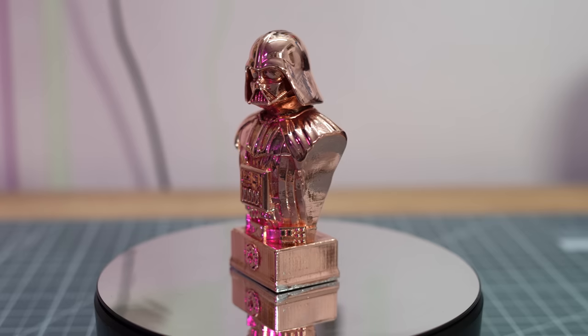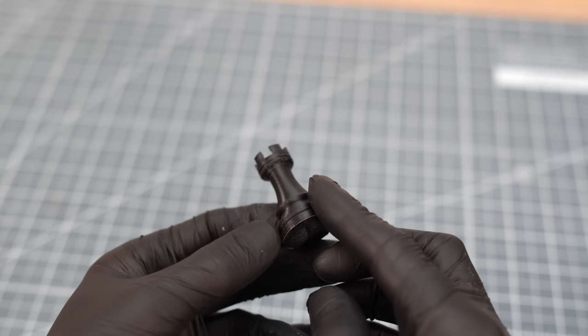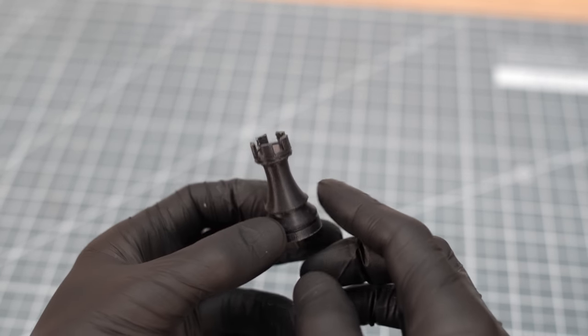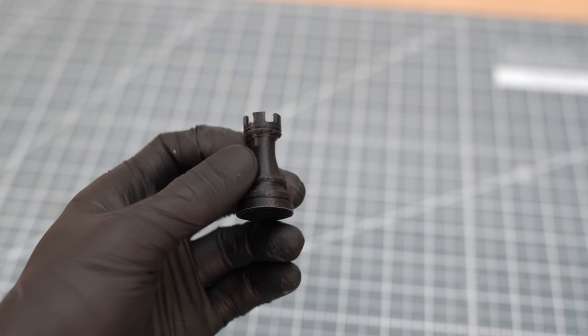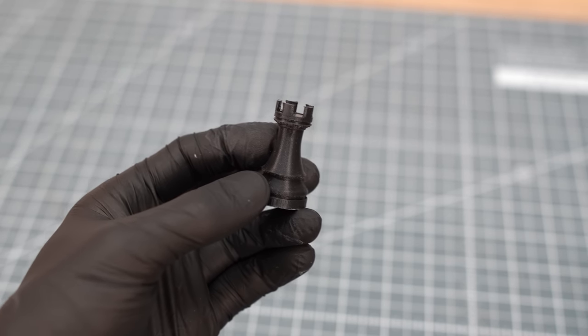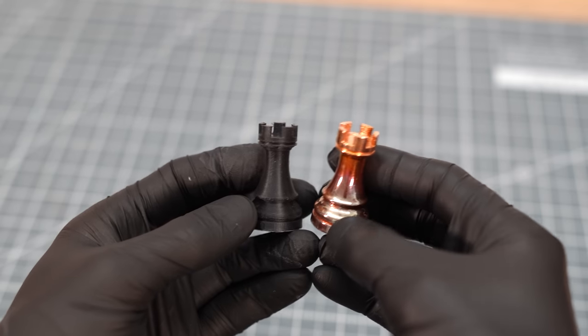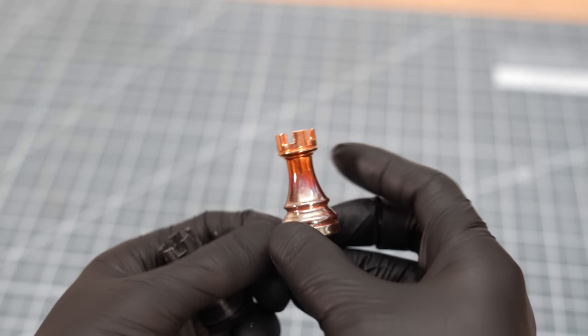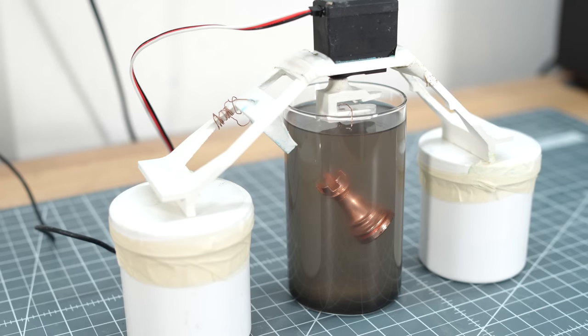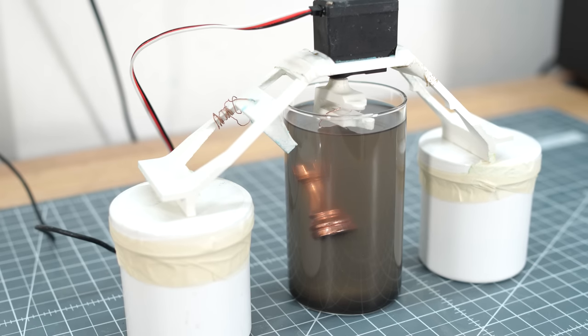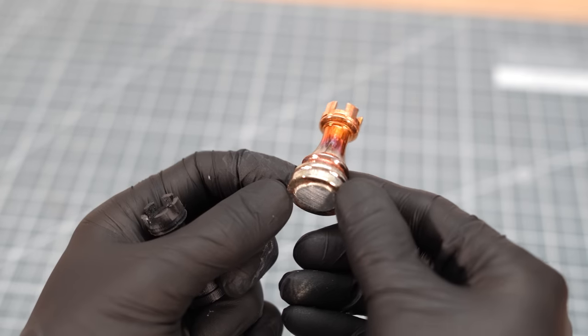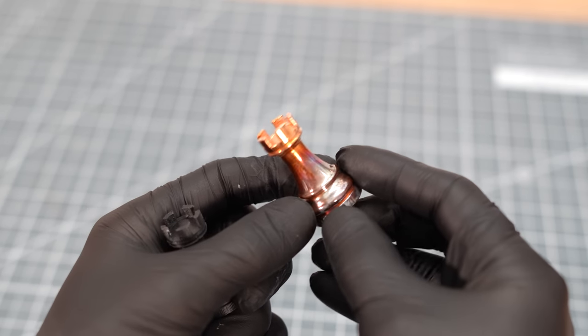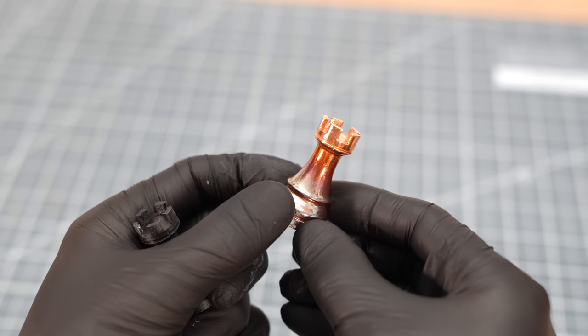Conclusion time. Should we follow this up? I was primarily interested in two things: one, to show that the electroform shell can be easily detached from the carrier, and secondly that it can then be cast. Personally, I think the PVB can only be completely dissolved with some effort. You need a lot of isopropanol and have to wait and stir more often for the PVB to dissolve completely.